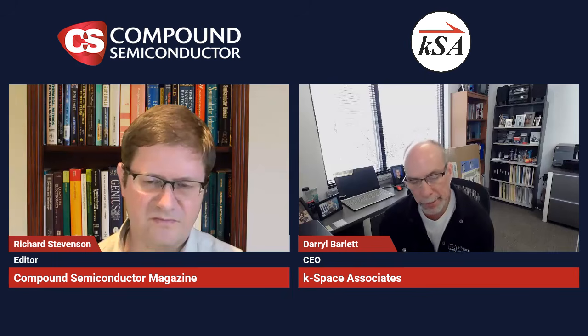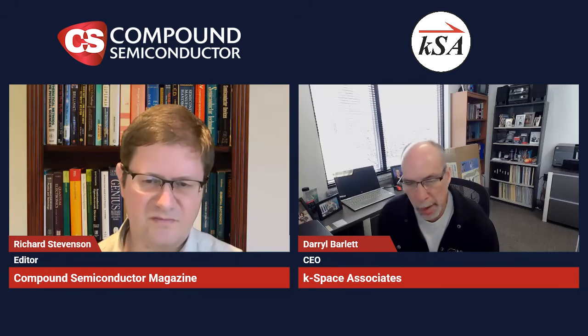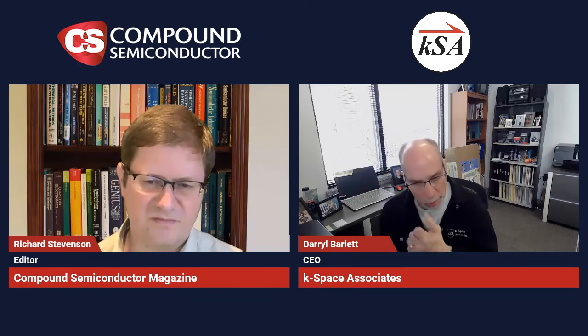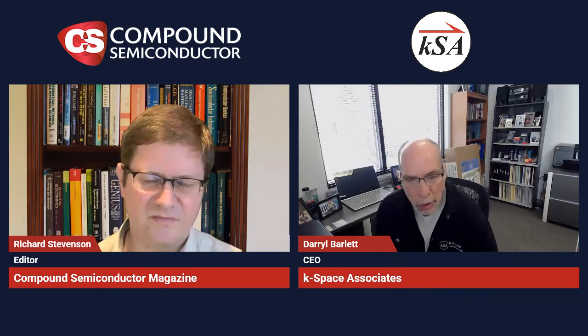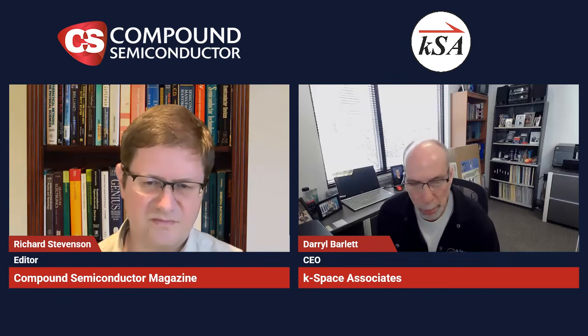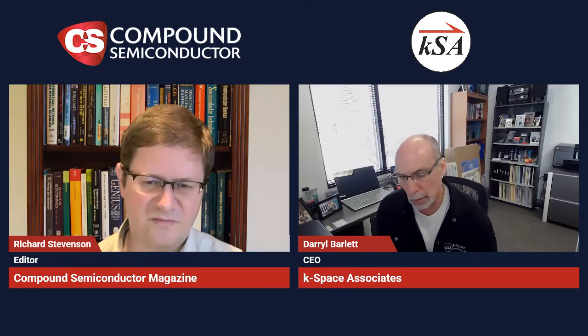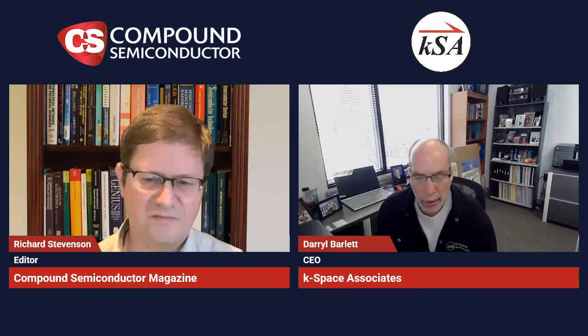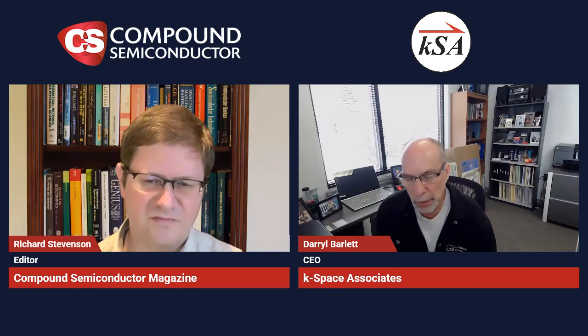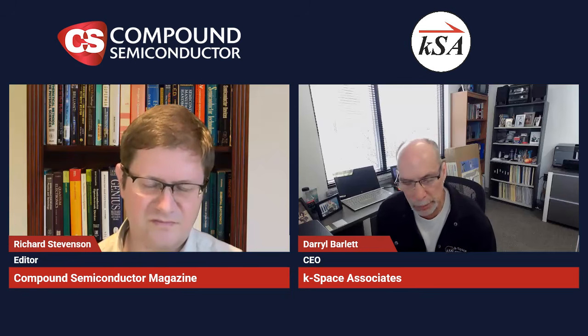We're also trying to add another temperature measurement technique to our Bandit system. Like I mentioned before, we can do band edge temperature, pyrometry, and blackbody measurement, but there are other materials where none of those techniques work really well. Some of the small band gaps, some of the highly doped materials. So we're adding what they call an E1 inflection point measurement. It's a spectral reflectivity measurement. We're adding it to Bandit to tackle some of those tougher materials and still get a good optical measurement of temperature. So those are a few of the things we have on the horizon.